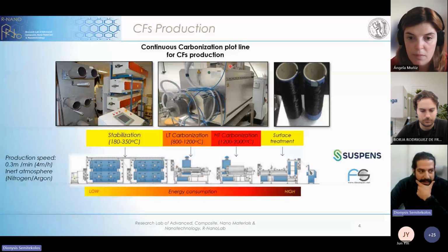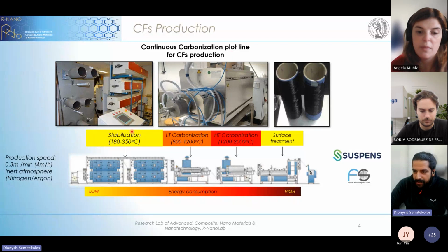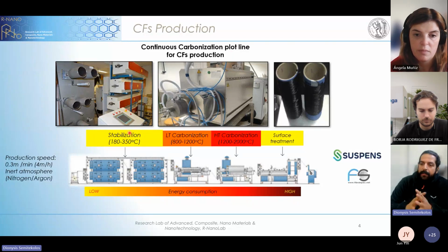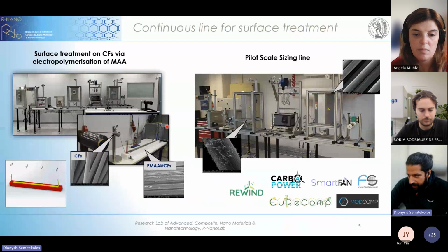About our capabilities in terms of composite materials and carbon fibers, we have some pilot lines starting from the stabilization of precursor fibers. We are now setting up the continuous line of carbonization, with another oven that comes parallel with the stabilization ovens. And we also have equipment related with the surface treatment and sizing of fibers. So we have designed and built these two lines.